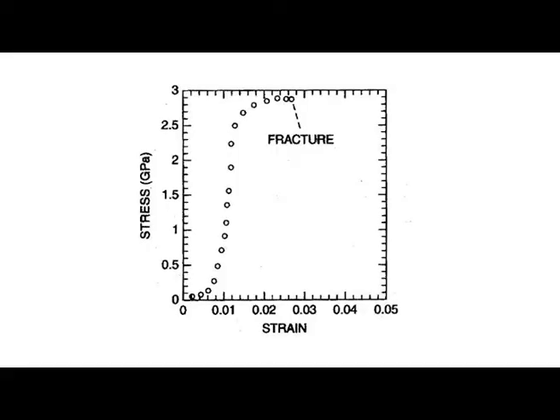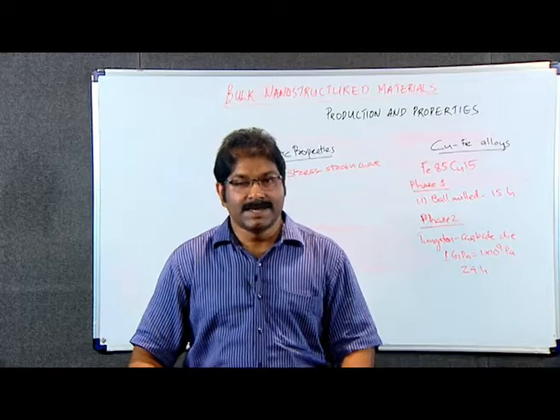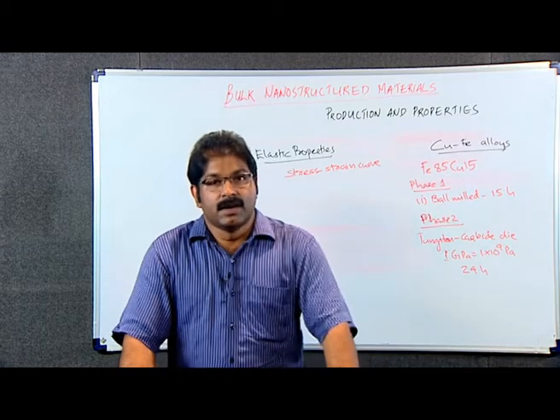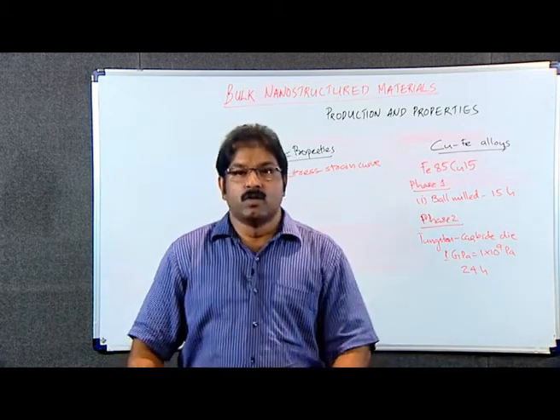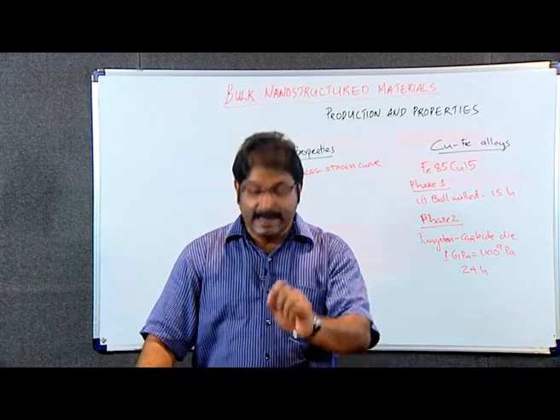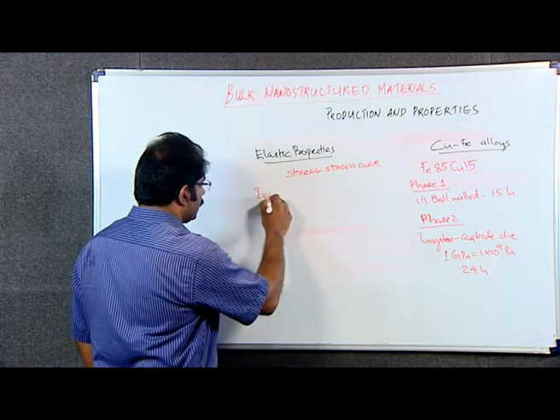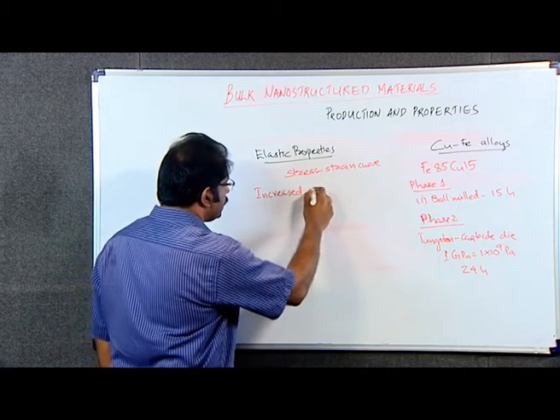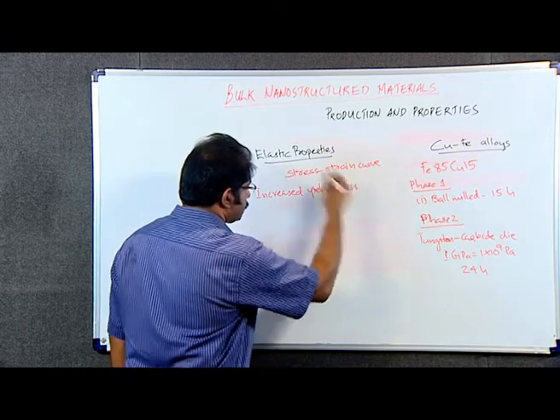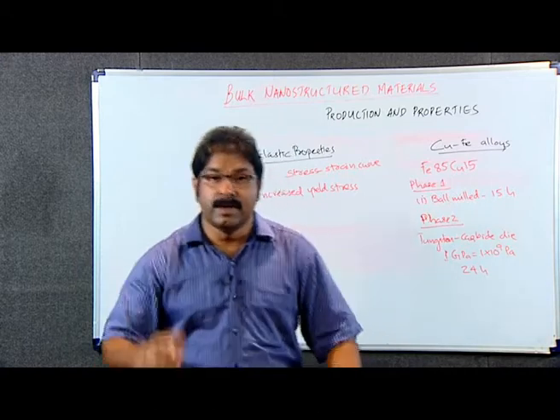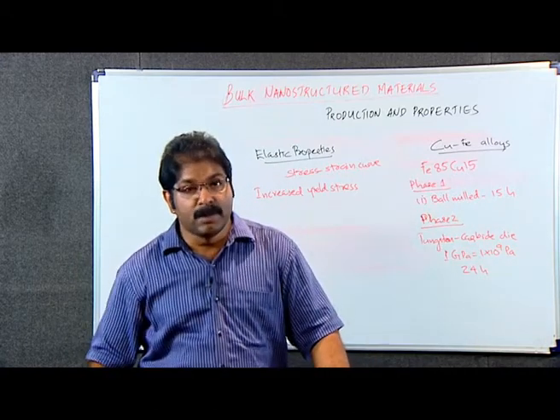In the curve, there is a ductile region which represents an elongation before fracture. The fracture occurs at 2.8 gigapascal, which is about 5 times the fracture stress of iron with grain size 50 to 150 micron. That is our normal iron. Hence, making materials with nano-sized grains will result in significant increase in yield stress, and can be used to make stronger materials, say for example, automobile bodies.